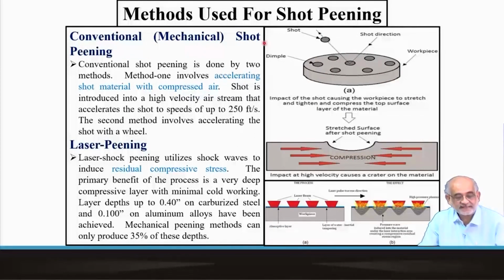Now, this mechanical process or shot peening process is pretty similar to laser peening operation, but we'll cover the laser peening operation in the next lecture. But it's very important to say that given a choice, and if precision is important, then obviously one will resort to laser peening. For the simple reason, if you read the last line, it says mechanical peening methods can only produce 35% of these depths, so this depth of useful stress zone creation. So, that means laser peening will be a lot more effective than mechanical shot peening.